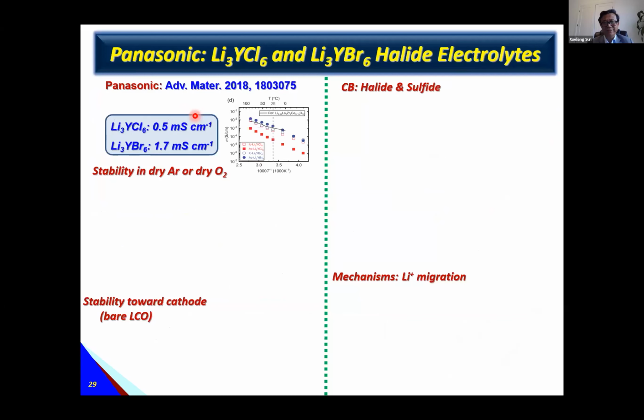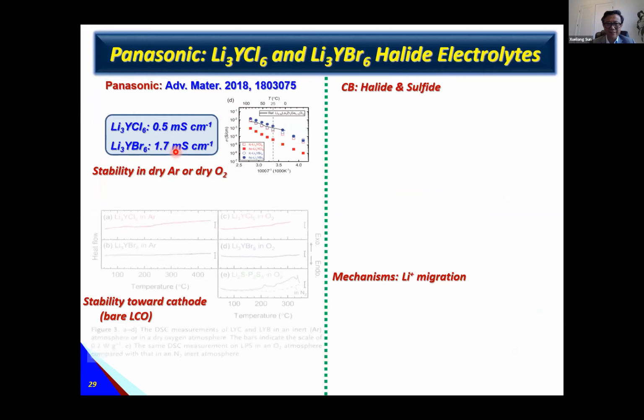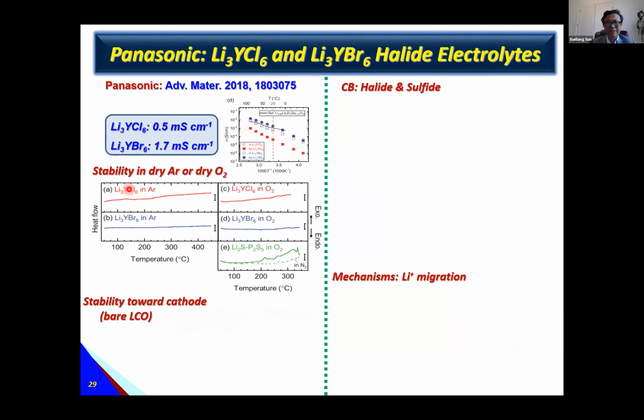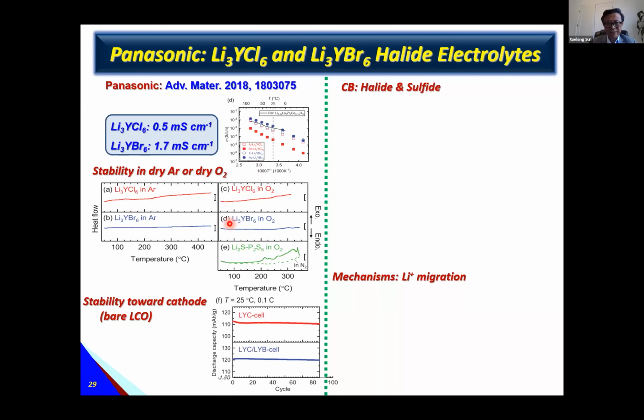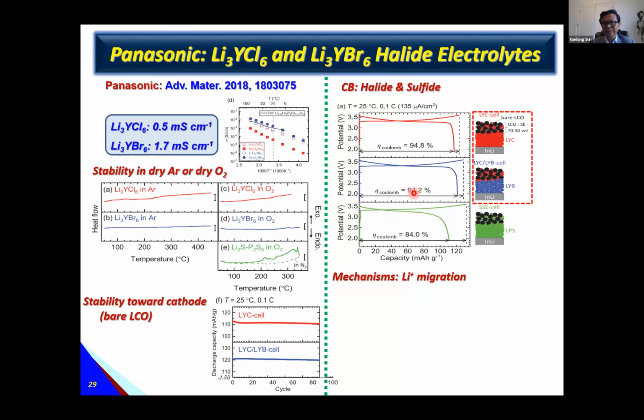So I'd like to give you the example from Panasonic. At the end of 2018, they reported lithium yttrium chloride and lithium yttrium bromide. They found a very high ionic conductivity in this system. They also found the solid-state electrolyte is stable in dry argon and dry oxygen environments. And even without coating on the cathode, the battery can run very well. For example, compared with sulfide-based, whose initial Coulombic efficiency is just 84%, the halide-based electrolyte maintains 94% Coulombic efficiency.